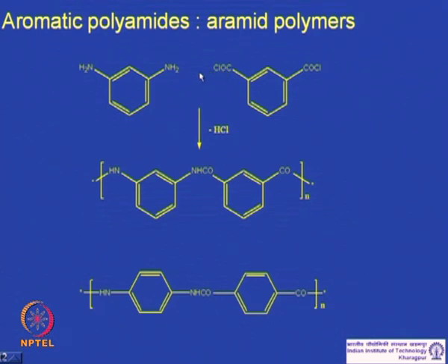In this case, we cannot simply do the polyamidation reaction with diamine and diacids. You require a much more reactive functional group. So, typically in case of aromatic polyamide synthesis, aromatic diamines are reacted with aromatic diacid chloride and you get completely aromatic polyamides. Instead, you can use the para-substituted diamine with para-substituted diacids to form these linear aromatic polyamides, and this is known